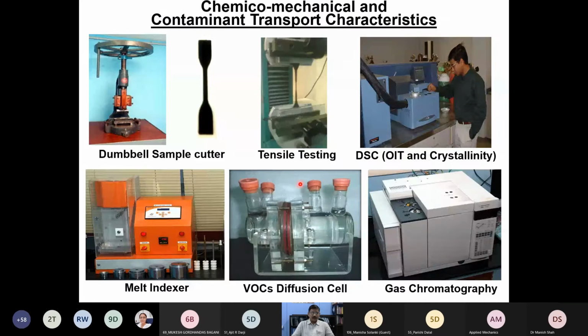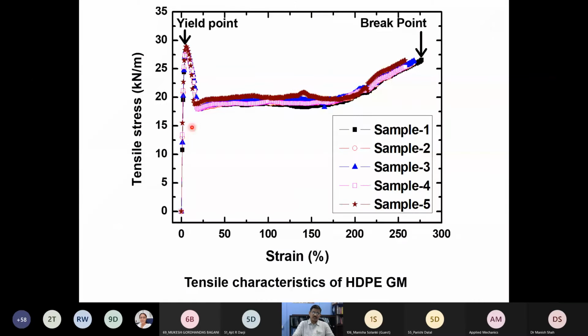Coming back to the mechanical performance of the polymer, even after exposure to a certain amount of radiation, you will see that the yield point and the break point didn't really change. Please note that in a UV weather testing equipment or Xenon arc, your sample is exposed to radiation on one side, and the other side is unexposed. So the weathering process always starts from the surface, and when you are doing mechanical testing, something like a tensile test, the entire bulk material is involved in the process. Meaning thereby, you may not really see the weathering initially by conducting the tensile test.